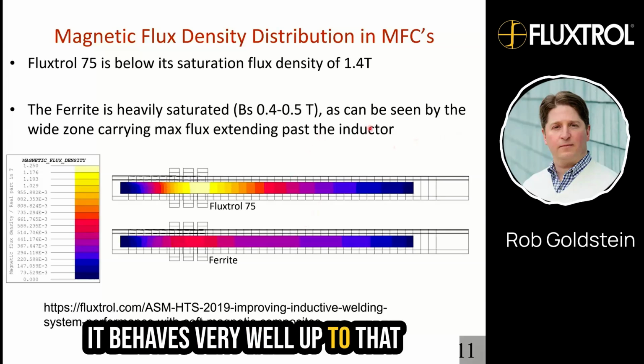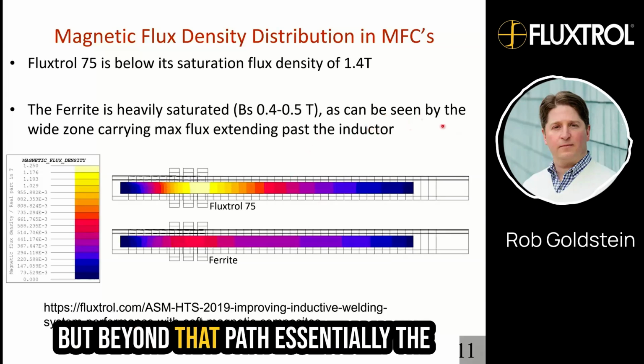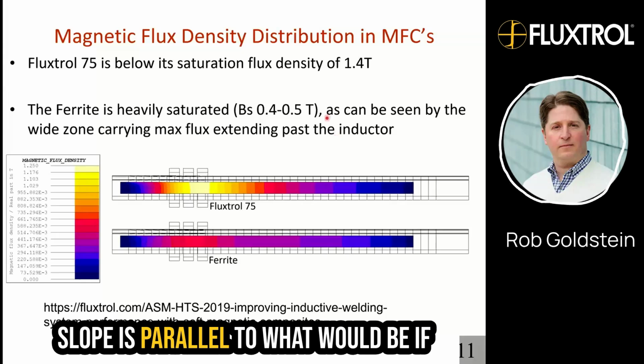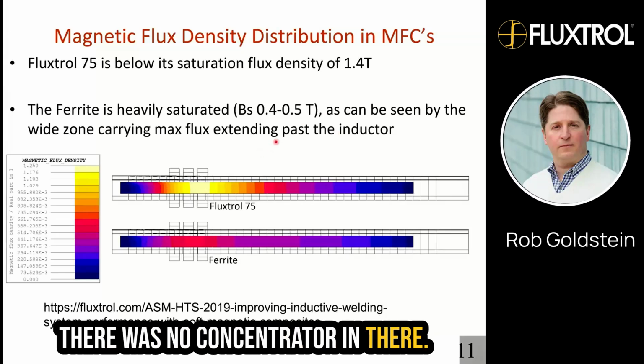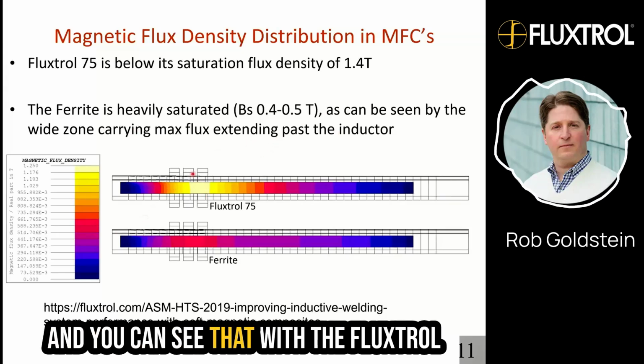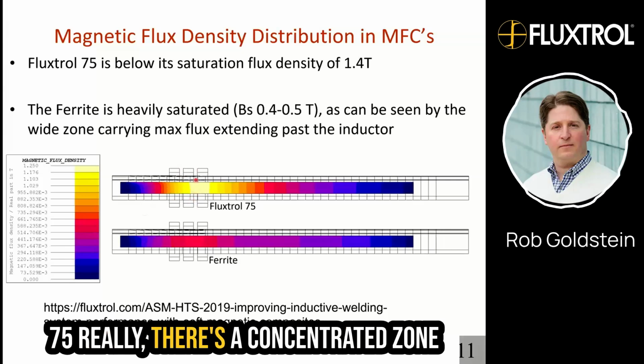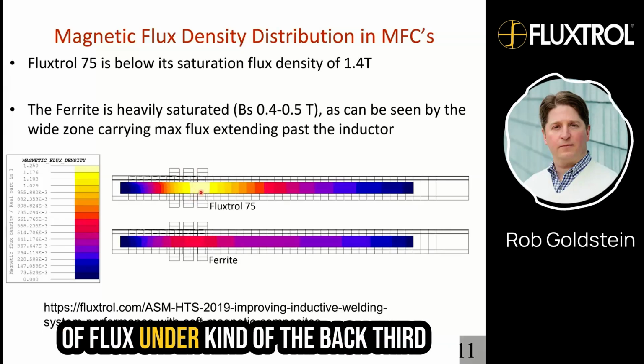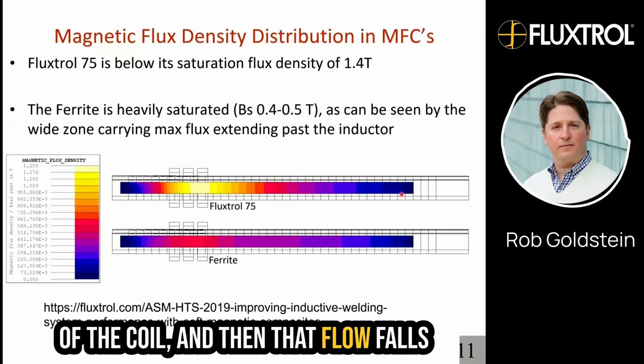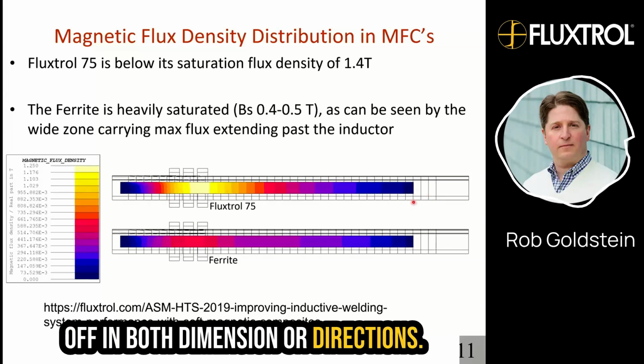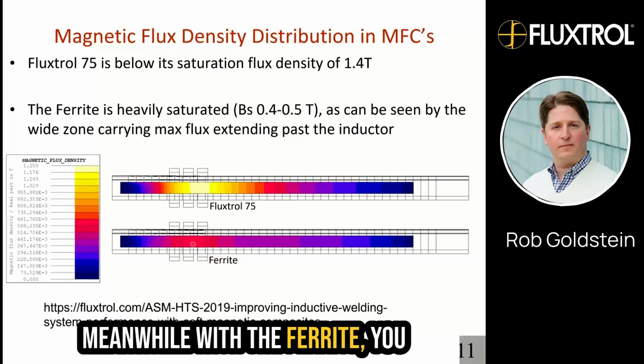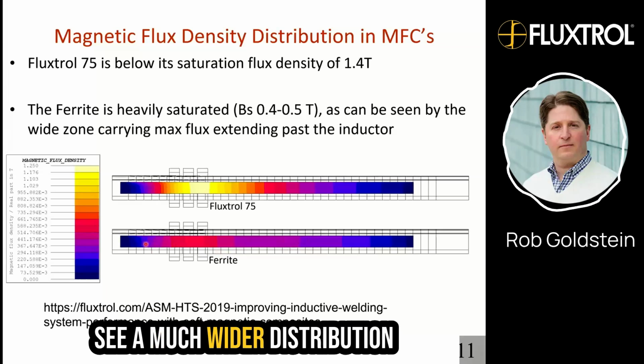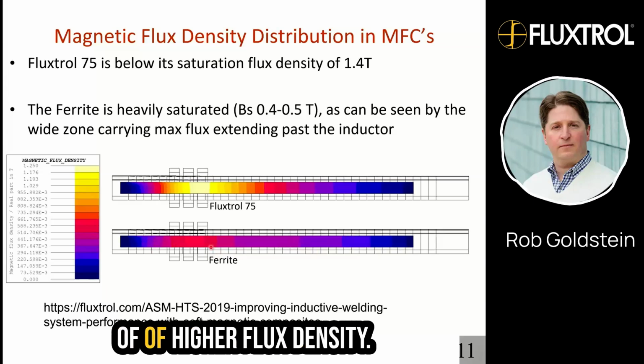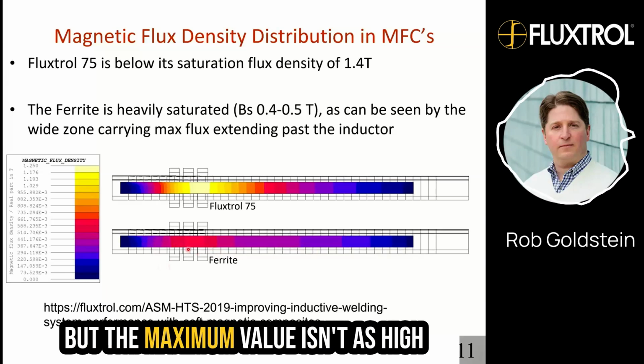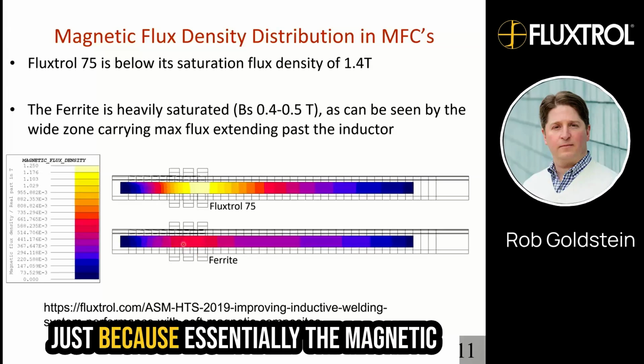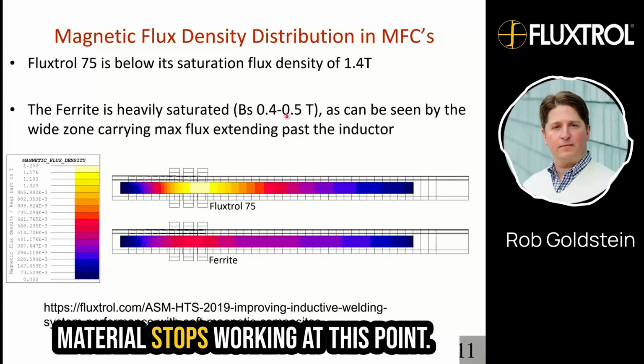It behaves very well up to that level, much more favorable path, but beyond that, essentially the slope is parallel to what would be if there was no concentrator in there. And you can see that with the Fluxtrol 75, really there's a concentrated zone of flux under kind of the back third of the coil, and then that falls off in both directions. Meanwhile, with the ferrite, you see a much wider distribution of higher flux density. But the maximum value isn't as high just because essentially the magnetic material stops working at this point.